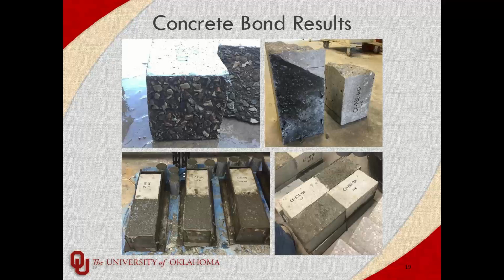So after pouring them and letting the UHPC cure for 28 days in ambient conditions, we tested those in third point bending, similar to the flexural test. Next slide.